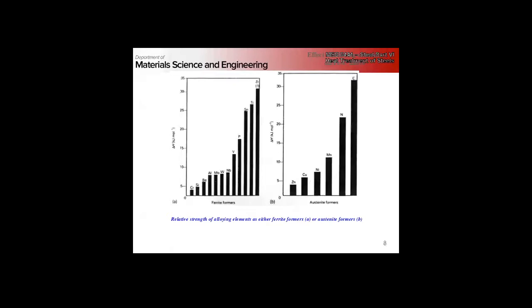I don't know of any commercial steel that uses hafnium, but my guess is that it would be an even more potent stabilizer than titanium or zirconium. Because it's the same family, but it's a larger radius, and the cubic hafnium phase is more stable than either titanium or zirconium. So I could guess as to what would happen, but I may be wrong there. So I don't really have an exact why.